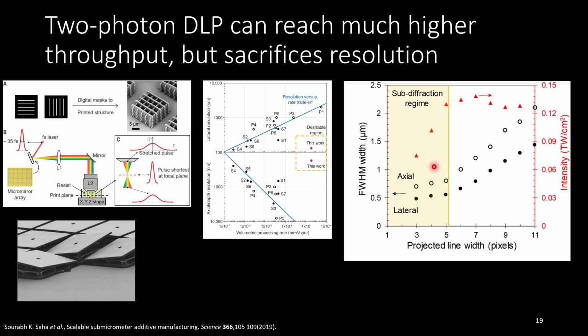You can recover that full single point diffraction limited resolution. But as soon as they start going to thicker lines, you start very quickly losing your axial resolution and get very extended PSFs, which then means you're losing the submicron resolution you want from 2-photon, and it means now you have a resolution that changes as a function of the shape that you're trying to make, which is pretty difficult to deal with in practice.